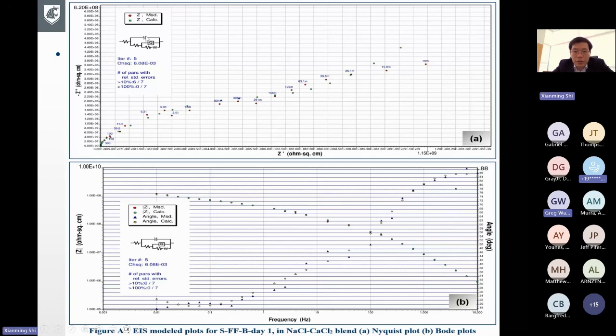In terms of that coating soaked with de-icer, it becomes a non-perfect capacitance or capacitor, and it has its own resistance. And then there's another combination of resistance and capacitance, where the capacitance is a so-called Warburg diffusion. This Q is another kind of capacitance, and this W is a Warburg diffusion resistance. Anyhow, these things actually tell you how fast corrosion is occurring at the metal to de-icer interface.